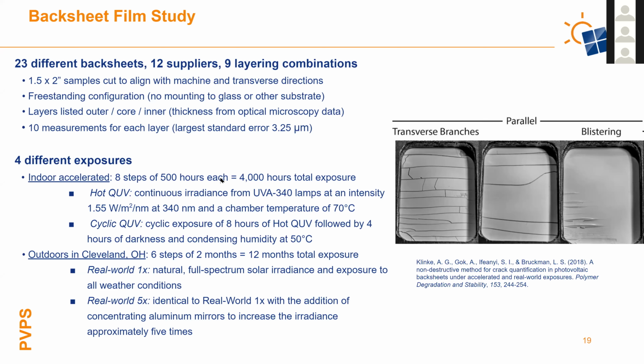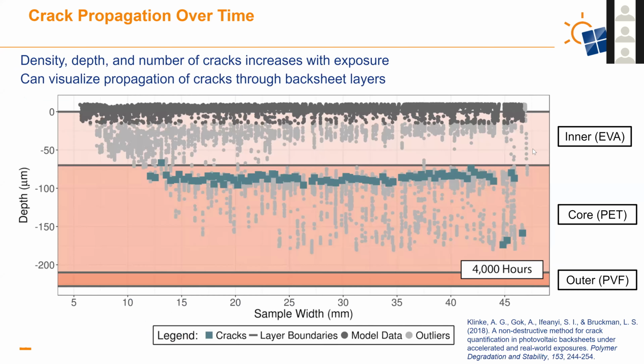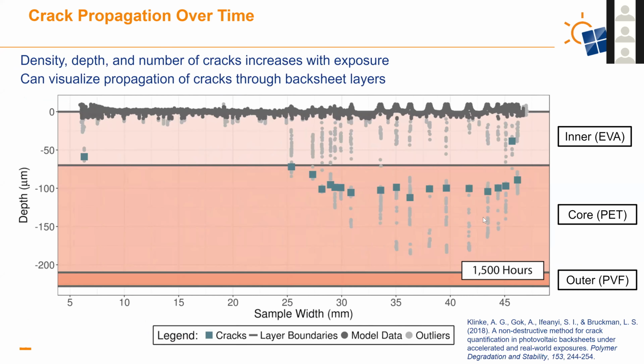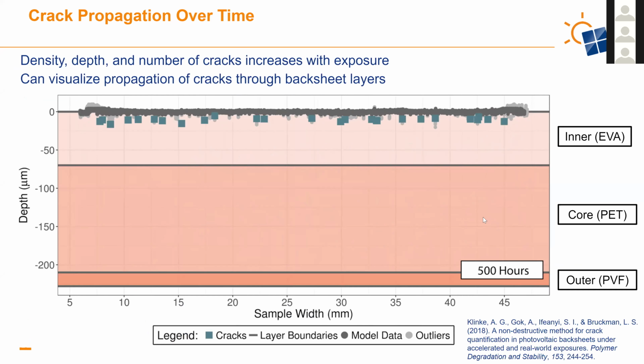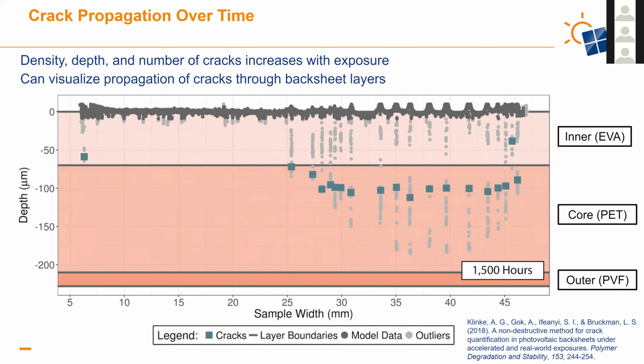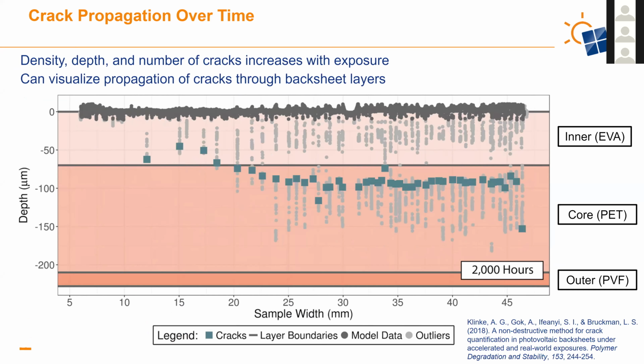And you could start seeing cracks forming about 500 to 1,000 hours from the inner layer, the EVA, to the core. So all of these actually crack from the inside to the core PET, where the outer layers were actually exposed to the light. So we had inner layer cracking first.